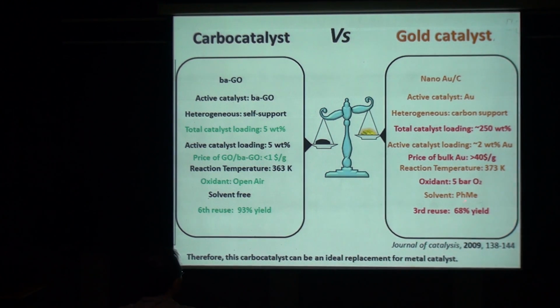For this reaction, the chemists normally use 5 bar molecular oxygen, pressurized oxygen, to catalyze. And they need to use solvent. Reusability is not very good. The yield is not good. Here is good use. We can use up to 6 reuses because we tested up to the 6th cycle. It's very good. So it seems like the graphene oxide itself, the carbon material with oxygen group, can behave as a catalyst, even compared to metal.